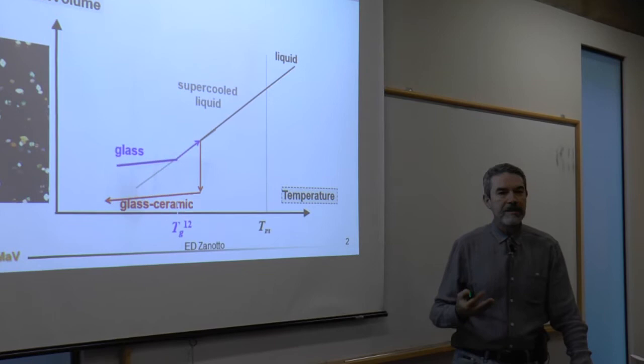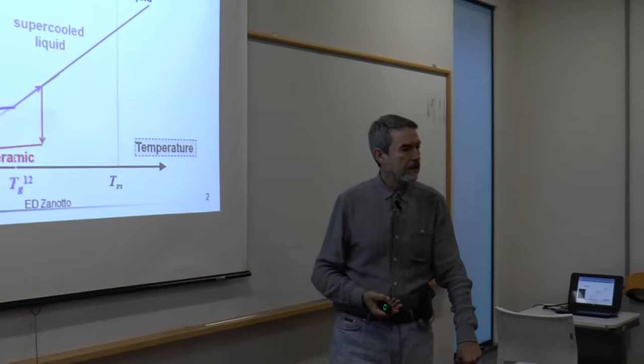So it has the right time scales for measurement in laboratory time scales. There are a lot of studies on lithium disilicate, but also other systems such as barium disilicate, calcium metasilicate, the 1-2-3 soda lime silica glass, 2-1-3 soda lime silica, lithium diborate, anorthite, and a few others. They show homogeneous nucleation in the bulk even without adding nucleating agents.